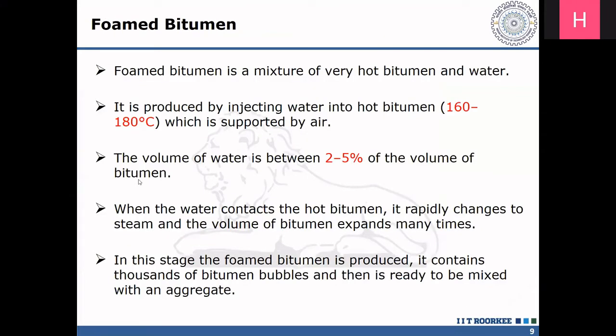Now, as I explained briefly, foam bitumen is a mixture of very hot bitumen and water. It is produced by injecting water into hot bitumen, maintaining the temperature between 160 to 180 degrees Celsius, supported by air. The volume of water is between 2 to 5% of the volume of the bitumen. When the water contacts the hot bitumen, it changes to steam, and the volume of bitumen expands many times, at least 15 times. In this stage, the foam bitumen is produced. It contains thousands of bitumen bubbles, and it is ready to mix with aggregate without giving any temperature.